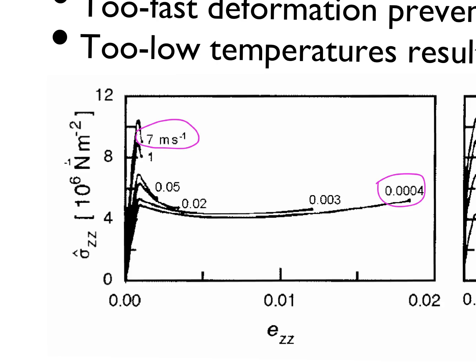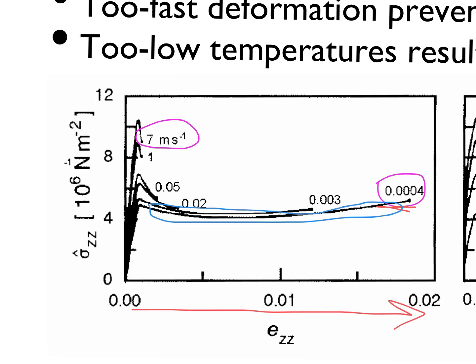You guys don't do this in the lab. What you see with these very slow strain rates is significant amounts of strain before fracture, and you're also looking at a long period of deformation. At this particular rate, because of the area under the curve, which is substantially larger, we would think, oh, this is PVC, it's pretty tough stuff. It goes out to these relatively large strains. But if we instead run it at 7 meters a second, it acts like a classic elastic material. It goes up, has a little bit of extension, then it breaks right away.